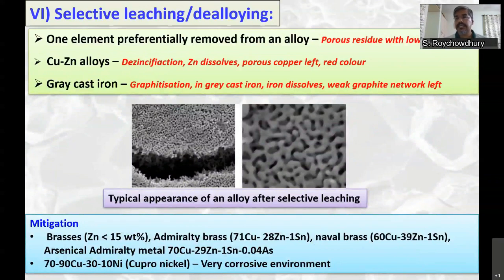Selective leaching, or dealloying, as the name suggests, of an alloy. One alloying component preferentially dissolves out or corrodes out, leaving behind such a porous structure which has very poor mechanical properties. A common example is dezincification in copper zinc alloys, where zinc dissolves out or corrodes out, and copper is left behind, which is porous. Also for gray cast iron, it is called graphitization, where you have graphite flakes, and this network of graphite flakes is left behind and iron dissolves. So again, it has weak mechanical properties, very poor, of this graphite flakes.